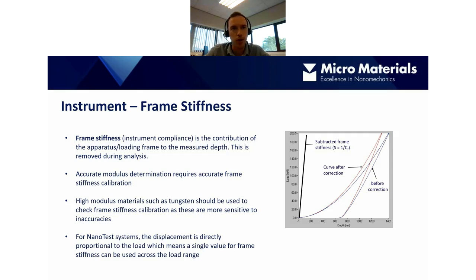So it is very important that the frame stiffness value is accurately determined, especially for high modulus materials such as tungsten, because if there's any inaccuracy, then it will significantly affect the reliability of the modulus values. For Nanotest systems, as it states here, the displacement is directly proportional to the load. That's why we get this straight line, which means we can use a single value for the frame stiffness across the whole load range. So we can do an experiment whereby we perform a range of different loads on the tungsten, and when we analyze the data, we get the correct modulus values across the load range.